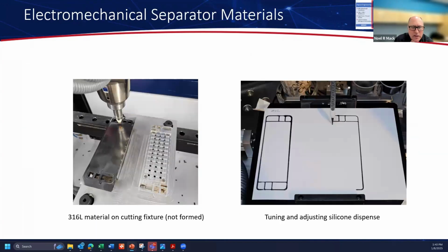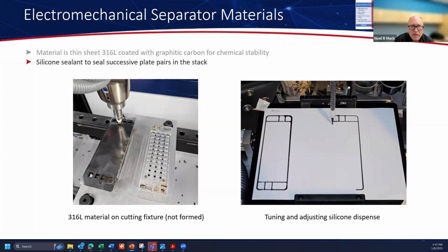So here's putting it into reality, taking this graphite coated 316 material in the cutting fixture. In this case, the graphic shows a non-formed plate. The plate form itself is controlled, so I won't show you the actual plate form, but here's showing a blank in the system. We need to form them. We need to laser cut, mark, laser weld, apply the silicon sealant bead, and then run the end-of-line pressure test. So in the graphic on the right, you see us working on tuning and adjusting silicon dispensing nozzles to be able to put the silicon seal down as well.